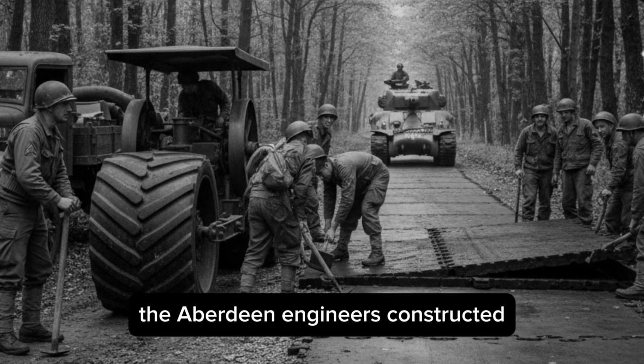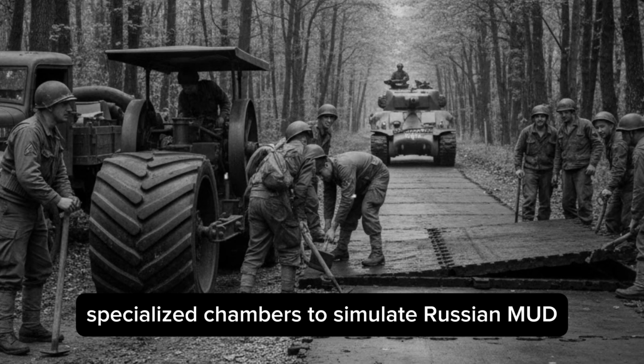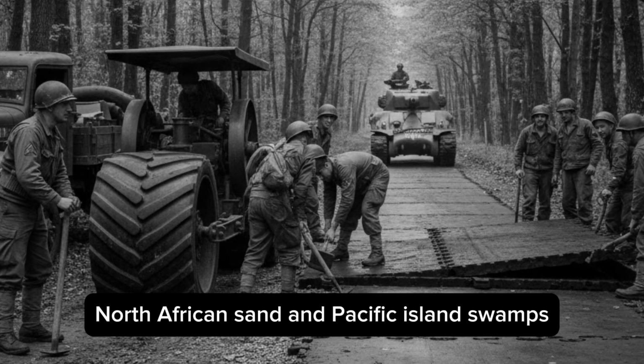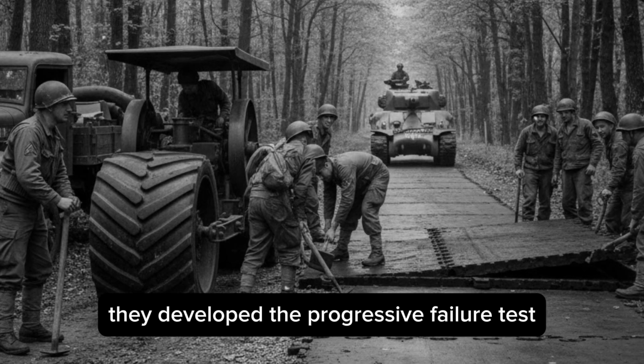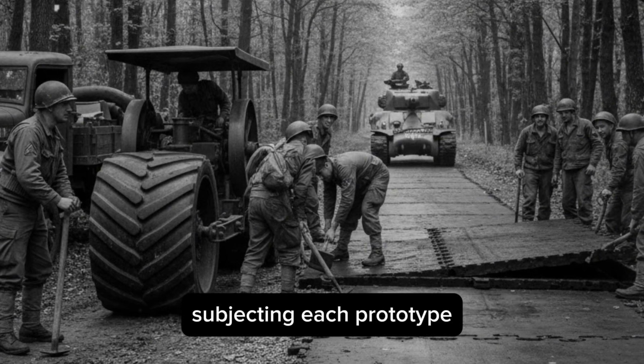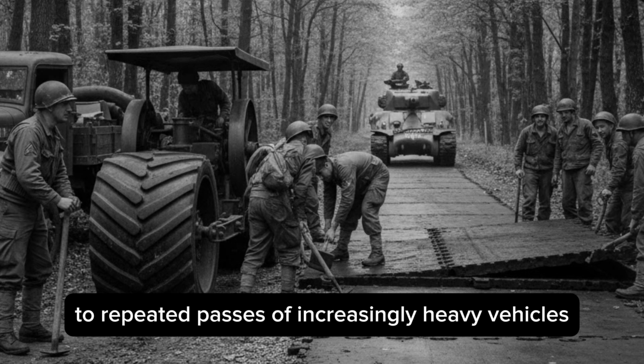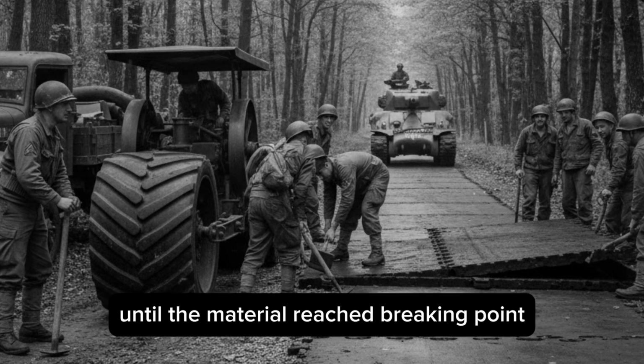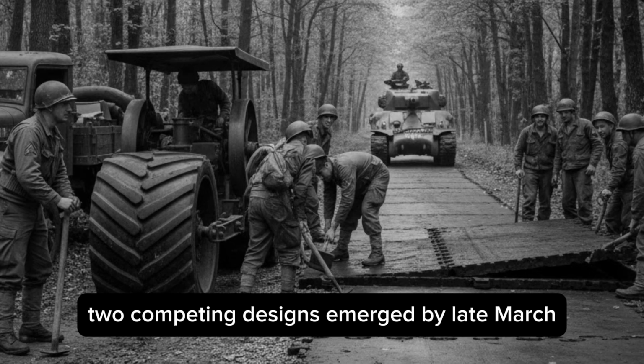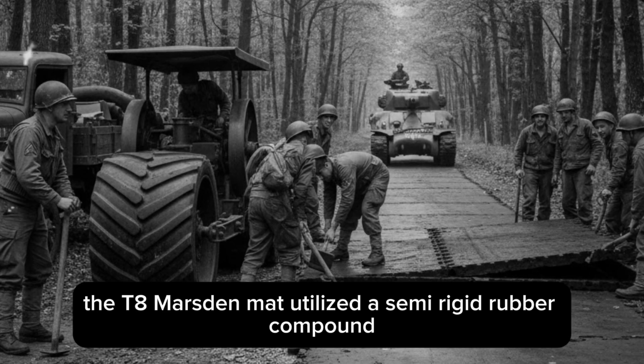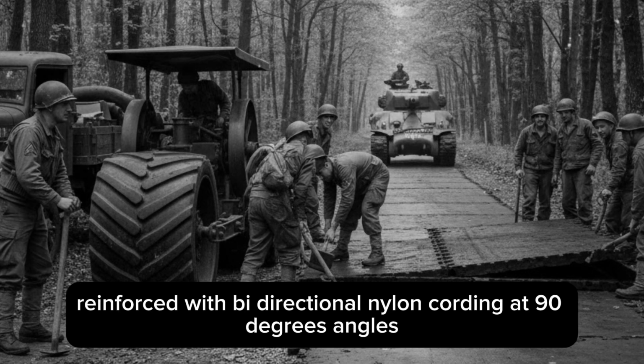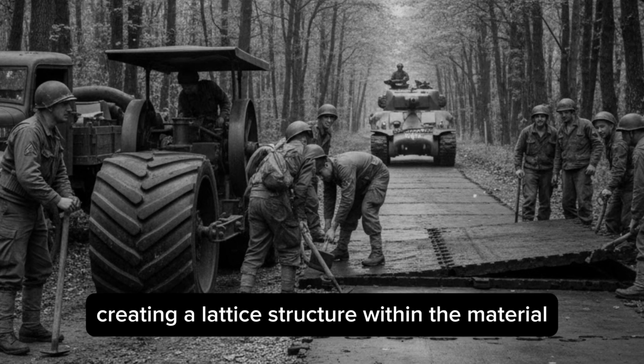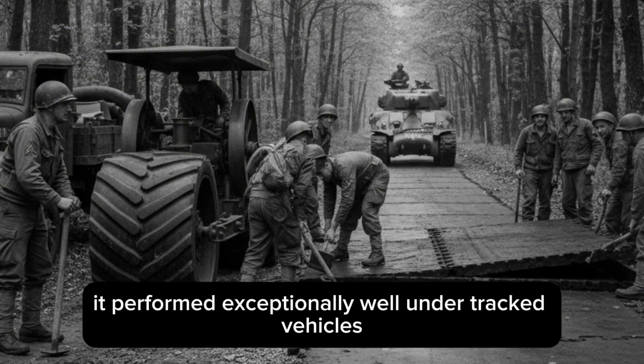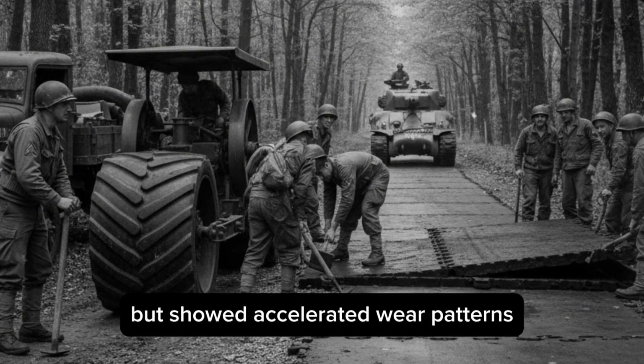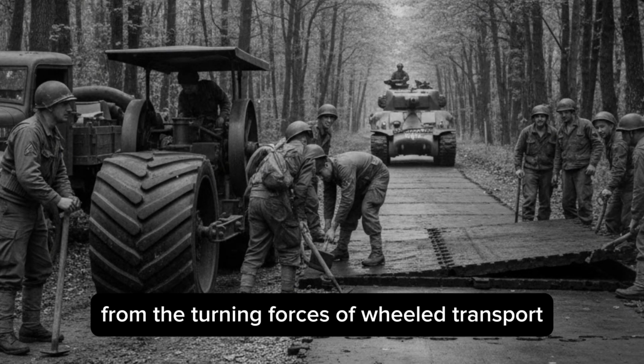The Aberdeen engineers constructed specialized chambers to simulate Russian mud, North African sand, and Pacific Island swamps. They developed the progressive failure test, subjecting each prototype to repeated passes of increasingly heavy vehicles until the material reached breaking point. Two competing designs emerged by late March. The T8 Marston mat utilized a semi-rigid rubber compound reinforced with bidirectional nylon cording at 90-degree angles, creating a lattice structure within the material. It performed exceptionally well under tracked vehicles, but showed accelerated wear patterns from the turning forces of wheeled transport.